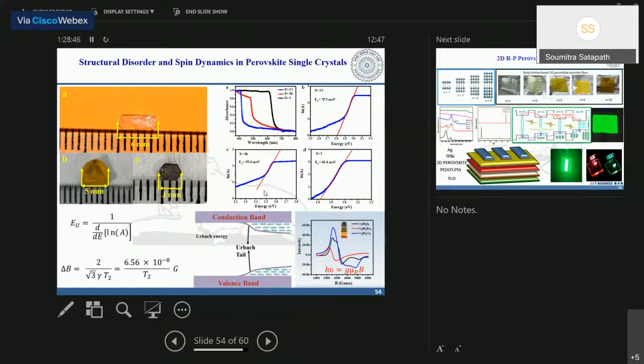And if you take a slope of that, that will give you the Urbach energy. And the Urbach energy of a system represents the disorderliness in the system. It is another, novel way of finding the disorderliness in the system. Now, in a crystal, you expect to see less disorderliness than in the polycrystalline material, and that's what we observe.